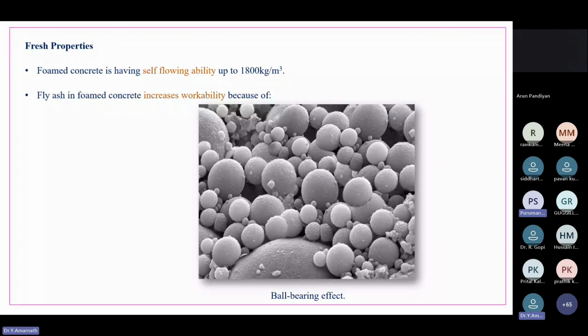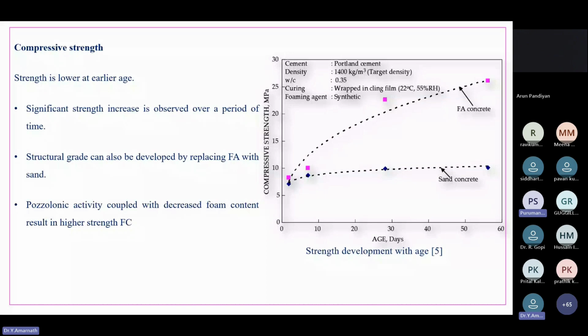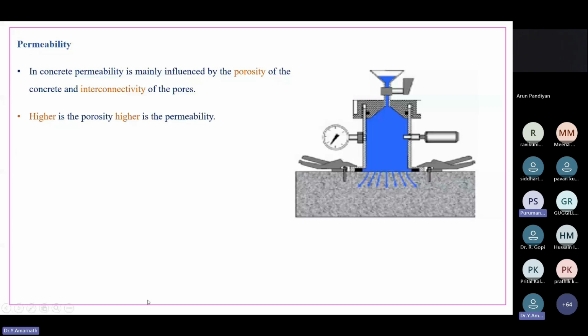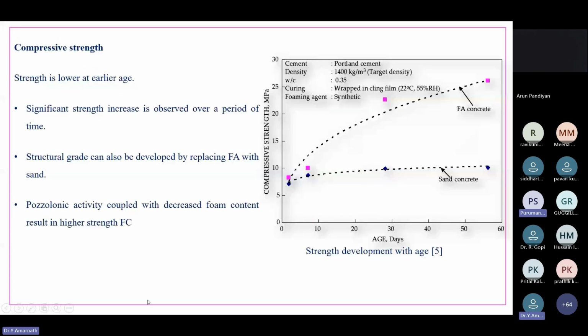Coming to a very important property of concrete, as well as foam concrete, the compressive strength of foam concrete. You can see here, this is one of the examples that I have taken from one of the research papers. In this particular graph, only Portland cement has been used as cement. The density of this particular concrete is 1400 kg per meter cube. Water cement ratio is 0.35. And then there are the curing conditions.